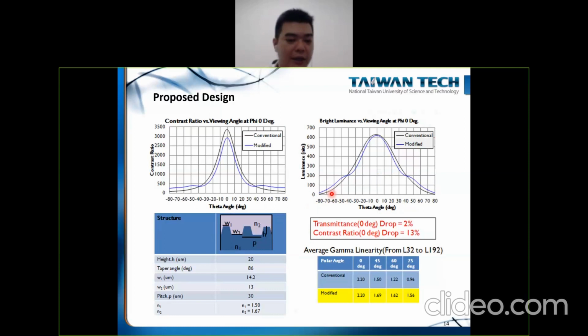Okay, and with a different width combination for the trapezoid structure, and the pitch is the period of this structure. And of course, we need to contact the supplier for the film fabrication to come up with this refractive index combination. They have different film materials with different refractive indices, and they have different epoxies with different refractive indices. Okay, so we come up with this combination.